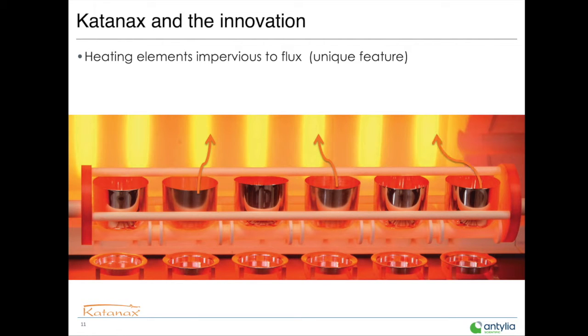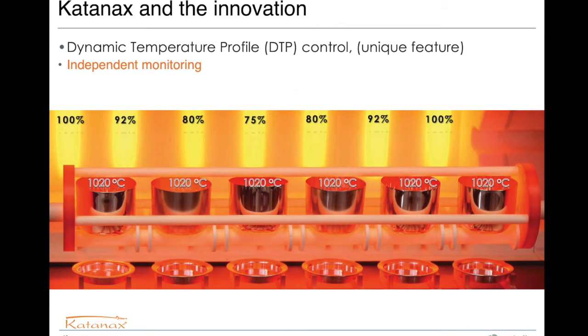One important aspect of our instrument is that our heating elements are impervious to flux, which is a unique feature. So basically, if you have projections of your mixture, including the flux, that go straight into the heating elements, they will be protected against that. We also have the dynamic temperature profile control, which means an independent control of each heating element. You need that to be able to reach a uniform temperature all across the furnace. So basically we can heat up more at the extremity of the furnace and less in the center.